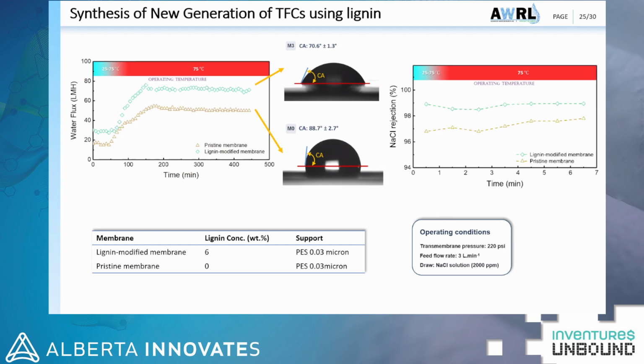So we usually have a trade-off relation between flux and rejection in membrane processes. When you increase the flux, salt rejection should decrease. But by adding lignin, we could get this result, which is repeatable, that we could increase both flux and rejection at the same time. But the most significant result is that both rejection and flux remain stable at 75 degrees C for the lignin-modified membranes. It means that lignin not only improved the permeation properties of the membrane, it also improved the thermal stability of the membrane.